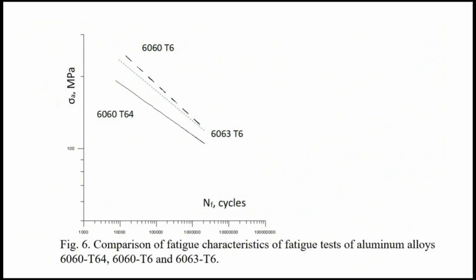We see that, similar to static, material 6060 T6 has higher stress, material 6060 T64 less, and 6063 T6 in the mean. But on the left, we see there is a big influence. When we prolong this characteristic on the right, you may see that after about 10 million cycles, it's nearly the same. For static, the strength is 2 times more for 6060, but in the fatigue problem, it doesn't matter what kind of material we use.